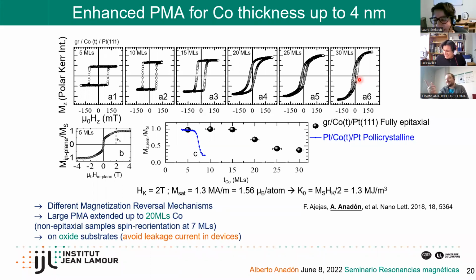Sorry, just to finish, one more thing. Graphene protects your cobalt, because normally if you grow a 5 nanometer cobalt layer and then you take it out of the ultra high vacuum, it's completely oxidized and you lose all the magnetic properties of your material. But for example, with one of these platinum cobalt graphene samples, like here, you can take the sample out of vacuum without any problem. And this is basically how this was done. You go to the magneto-optical Kerr microscope, and you measure the hysteresis loop out of vacuum because graphene protects your cobalt layer. This is another of the applications of graphene.